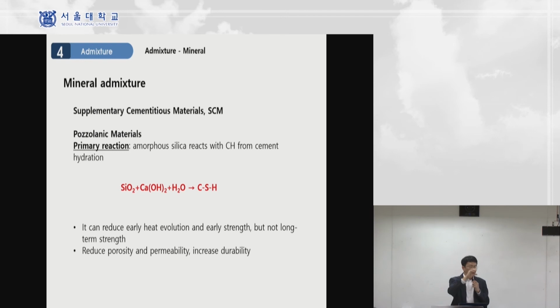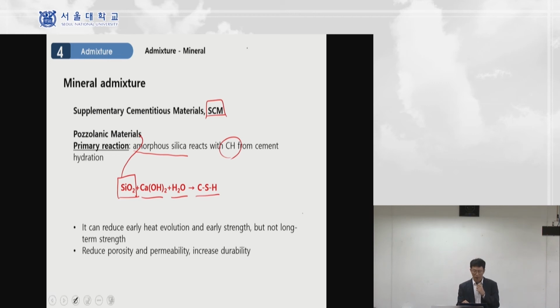All of these belong to the classification of the pozzolanic reaction. So what is the main primary reaction of this pozzolanic material? In the pozzolanic material, the amorphous silica, in class C or class F fly ash or silica fume, is the only reacting part so far, and it will react with calcium hydroxide and water and produce calcium silicate hydrate. So please try to remember this kind of chemical reaction, because this SiO2 from the pozzolanic material, SCM, and the Ca(OH)2, if you recall, the origin of the Ca(OH)2 is coming from the hydration reaction.